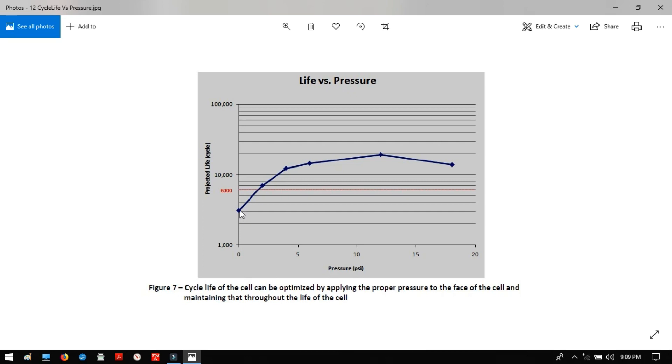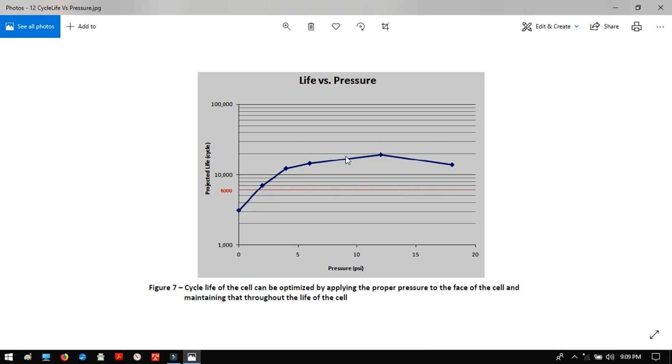Now, how you're going to do that in real-world applications starts to get complicated. Now, a rigid cell, a rigid case, which they do have like square solid plastic and cylindrical metal ones that hold the shape, kind of do some of this. So as it charges and discharges, the internal pressures will automatically increase to hold some of those things in. Now, as long as that means that the internal pressures don't pass this beneficial point, then you're fine. And that will get back into what temperature you're at, how fast are you doing it, and what state of charge you're at. But whether or not you've gone past the beneficial point. But if you have a rigid container, then it will increase internal pressure because it doesn't have as much. It can't physically swell or deform at this zero PSI point.